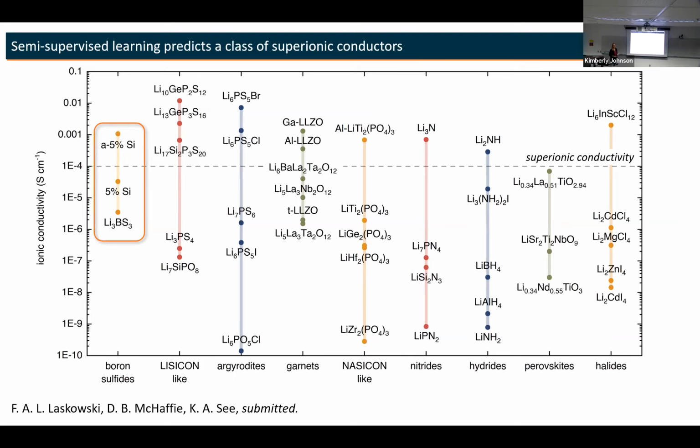magnesium, calcium, and zinc? Yeah, we're trying to develop solid state ion conductors for multivalent cations. Those are different materials than the lithium containing materials. Is it going to be the same material for the different cations? No, different materials. We found that if you try to superimpose a divalent cation onto a monovalent ion's conduction pathway, it's like a recipe for failure. So you need to develop a new material specifically for divalents in order to get it to work.